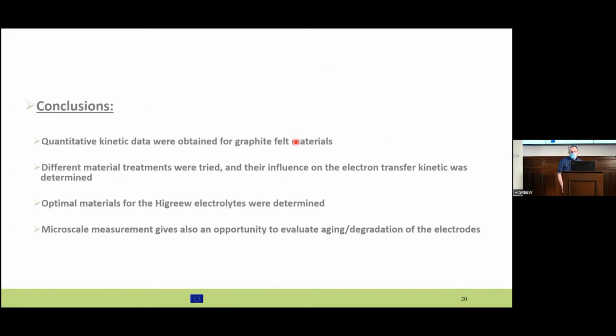So I come to the conclusion. We could perform quantitative kinetic analysis on graphite felt material. So you see, we try different approaches in order to be accurate. This quantitative assessment is important because this allows us to conclude clearly what are the best treatment for the HIGREEW electrolyte. And we identify this material.